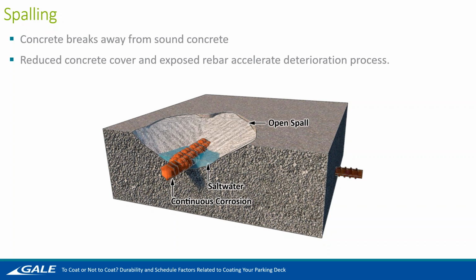As you can see in the image below, the salt-laden water is just coating the rebar, letting it pool around it and allowing it to go deeper into the other concrete and possibly get to that second layer of rebar. It just makes the problem worse as it keeps going, and the spall will only grow as long as it has remained open.